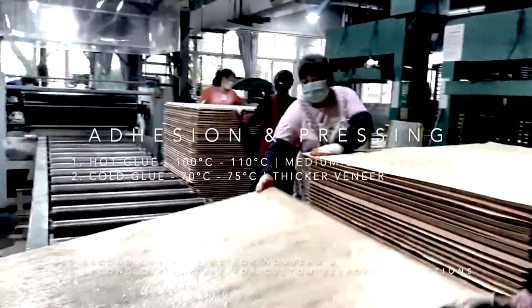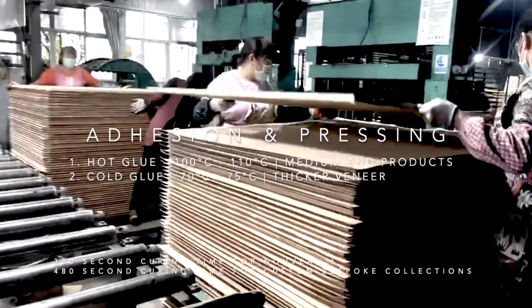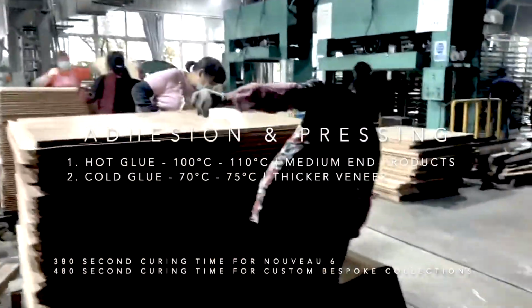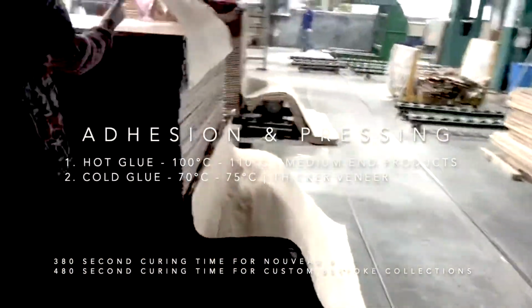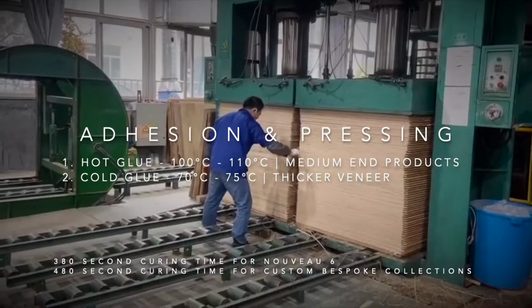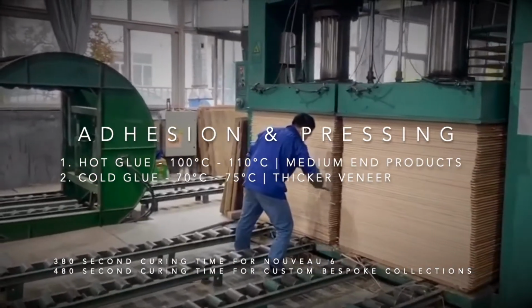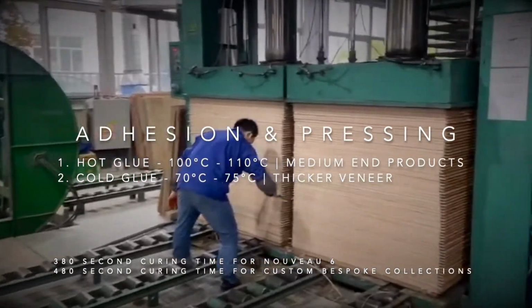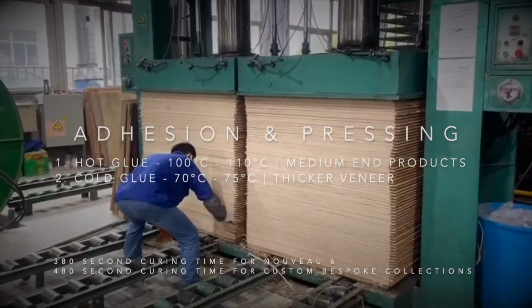Phase 5, adhesion and pressing. There are two types of adhesives we use at Biyork: a hot adhesive, which requires temperatures between 100 and 110 degrees Celsius when pressed, and a colder adhesive, typically used for thicker veneers, that requires temperatures between 70 and 75 degrees Celsius when pressed.